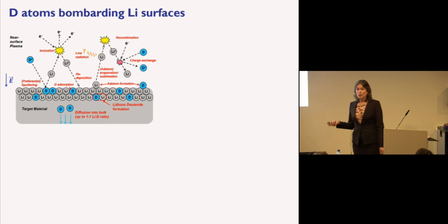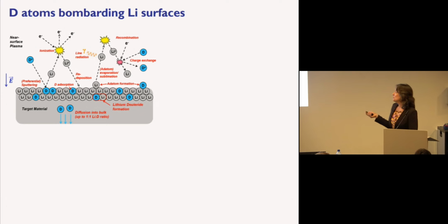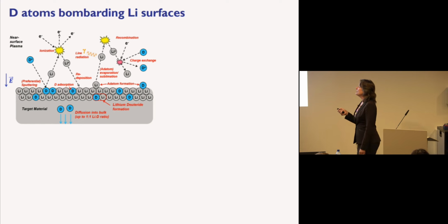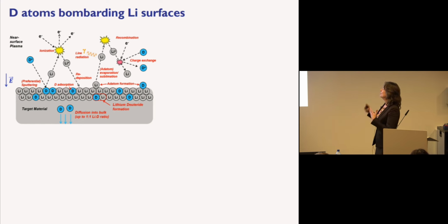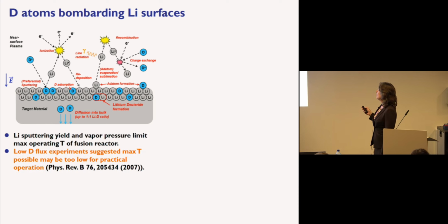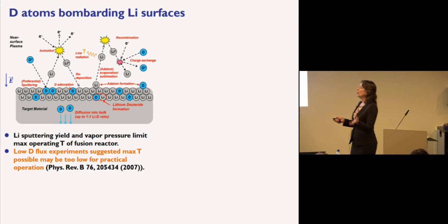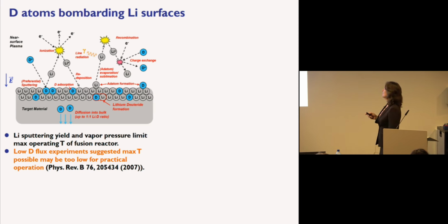So the real issue, though, is how to describe this horrible situation where you've got deuterium ions and potentially tritium ions hitting this liquid lithium, and then trying to understand what's going on there. And so there have been experiments. In fact, more than 10 years ago there were low deuterium flux experiments that suggested that there might be a maximum temperature that would be too low for practical operation, because essentially there seemed to be, under low deuterium flux conditions, too much lithium sputtering off of the liquid film.